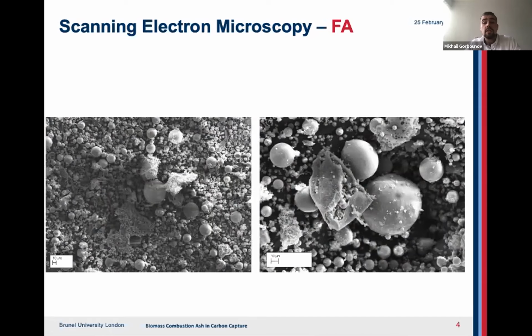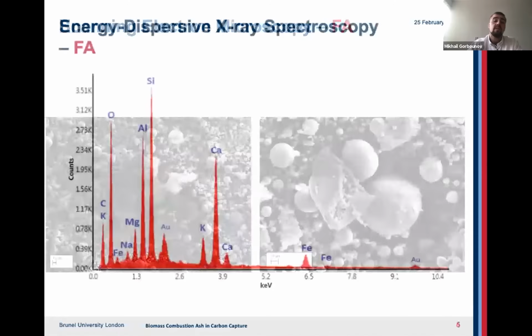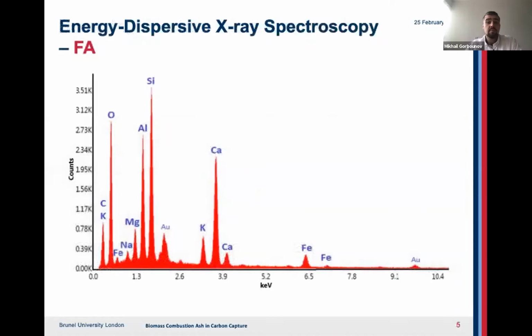Apart from the morphology, the elemental composition of the sample was studied using the EDS technique. And this method facilitates an understanding of the elements present in the material. On the slide, you can see the spectrum taken from our fly ash sample. As can be inferred from the picture, the material mainly consists of aluminium, oxygen, and silicon. These are the prevailing elements in the investigated ash, and such results were expected.